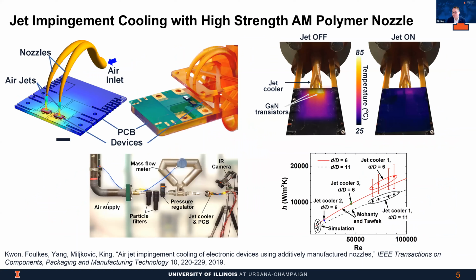Because this material is so strong, we started brainstorming what are some other things that you could do with an extremely strong and temperature stable polymer material. And that led us in the direction of the second project here, where we developed a jet impingement cooling apparatus that leverages an additively manufactured nozzle. So here we have 2 gallium nitride power electronic devices that are mounted here on a PCB board. We have high pressure air that enters the manifold, and then the nozzles direct the air immediately upon the devices while they're working.